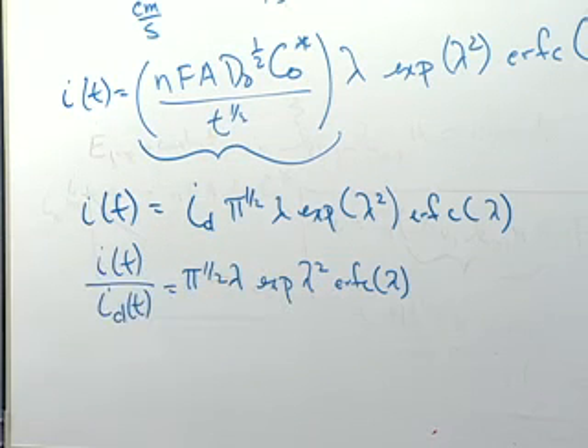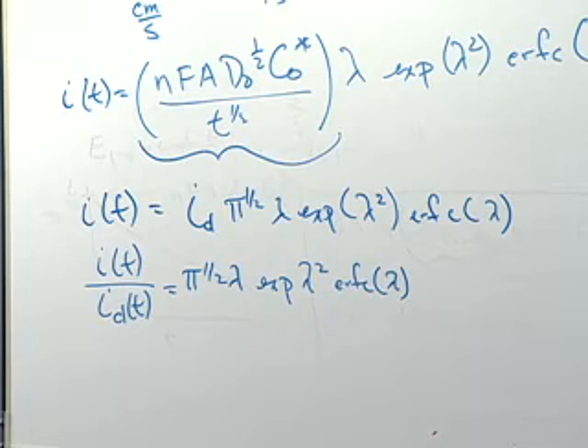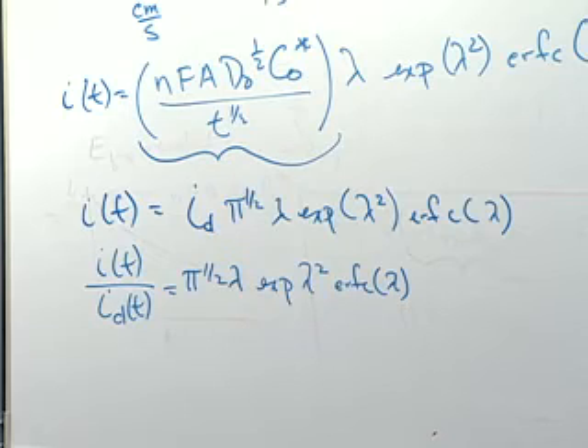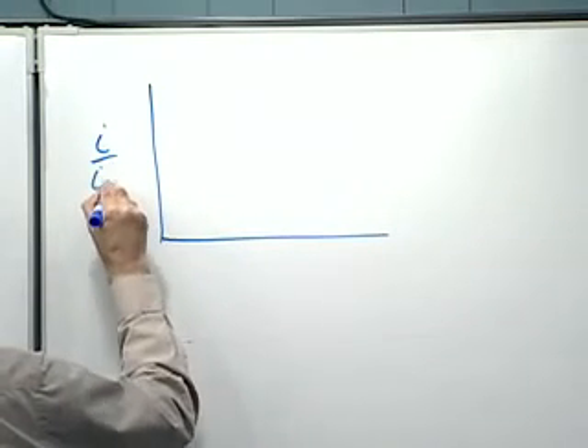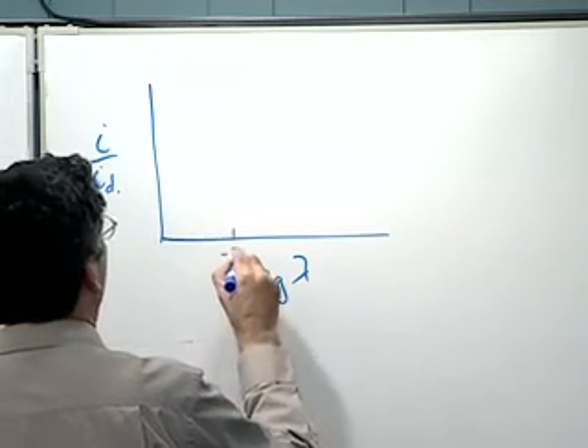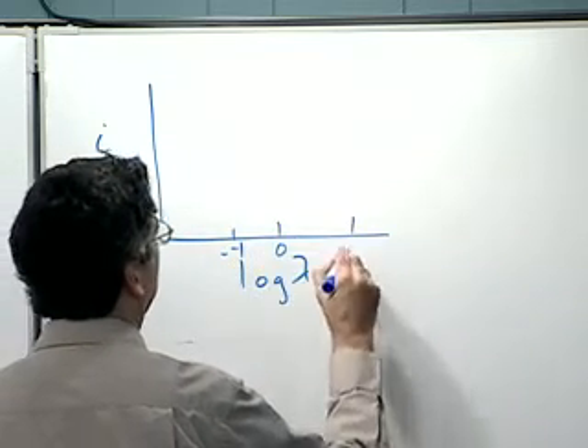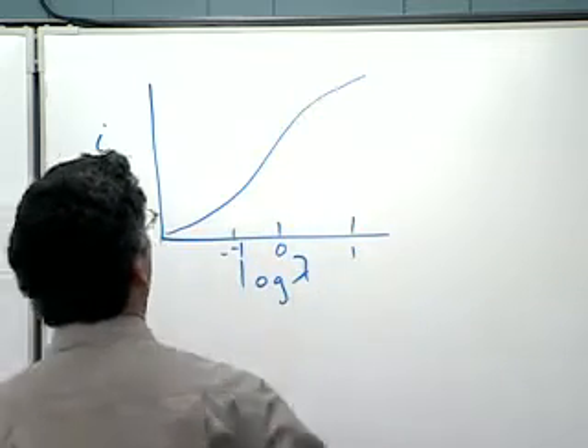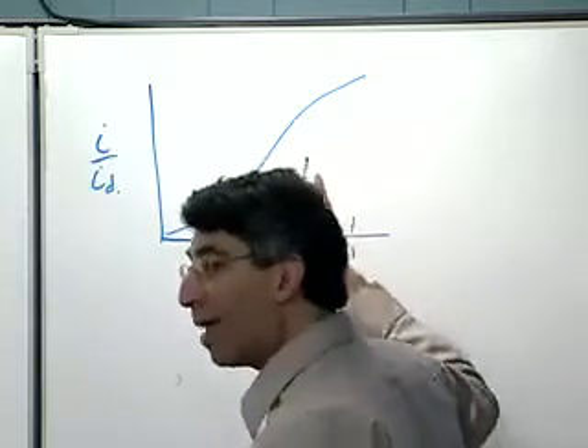Okay, now clearly on the right-hand side of the equation, I have dimensionless because I've designed it that way. But you'll also notice I've designed it so on the left-hand side of the equation, I am dimensionless. Doesn't matter if I measure my currents in amps or picoamps. On the left-hand side, doesn't matter if I use hours or fortnights, on the right-hand side of the equation holds nicely. Okay. So now I can take this equation and I can plot it. And there's a lot of different ways one might plot this equation, but it turns out in this particular case, the way one gets a fairly useful curve is by plotting the ratio of the currents versus the log of this lambda parameter. And if you do that, you get something that looks like that. And so we have a unitless or dimensionless working curve here.